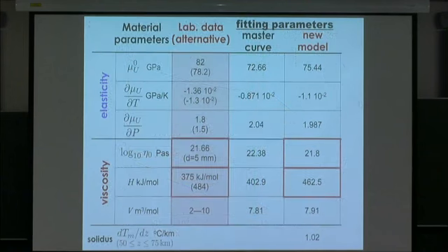And here the obtained fitting parameters are summarized. And viscosity and activation energy agree well with the experimental data obtained for olivine aggregates. And other parameters are also reasonable.